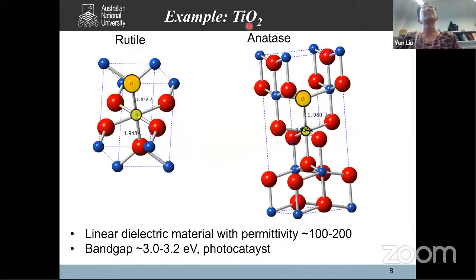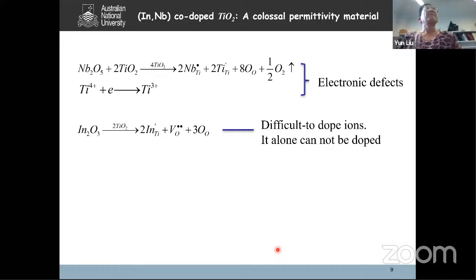Titanium dioxide generally has two structures at room temperature, rutile or anatase. Both are linear dielectric materials with permittivity around 100 to 200. Their band gap is around 3 eV. So if we choose titanium dioxide as a photocatalyst, it is pretty much only sensitive to UV light. Okay. So in that case, people have done a lot of work, like introducing niobium into titanium.